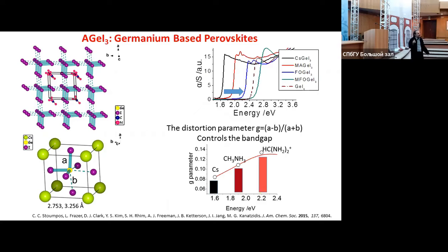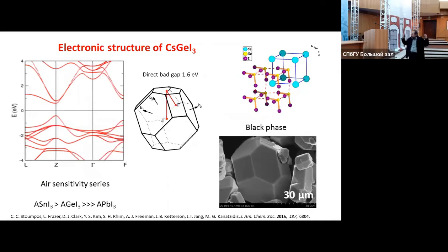In this case, it is this distance that determines orbital overlap, and if you establish a parameter that connects this distance with this distance, you can find a trend that correlates bandgap depending on the distance between the pyramidal units. And if you plot the electronic band structure, it's still the same.